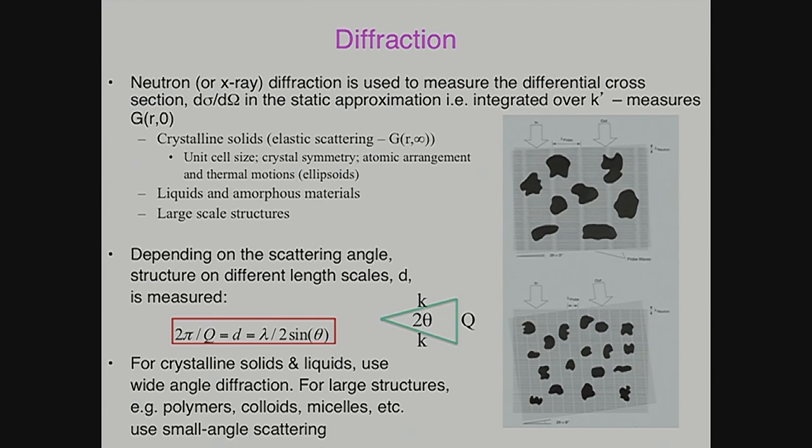If you have a larger angle, which is what's in this view graph, you can see there's the different angle. This is the angle here. Then the Moiré fringe pattern has a shorter wavelength, so you're essentially probing smaller D spacings. So you will see in the literature small angle neutron scattering, for example. Small angle neutron scattering means the angle between the incident and the scattered wave vectors is small. So you're basically probing large distances. You have to be careful in thinking, well, I'm probing exactly that distance, but it's generally true that you are probing large distances at small Q.